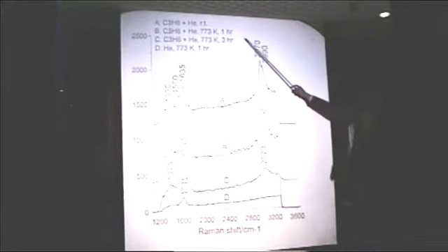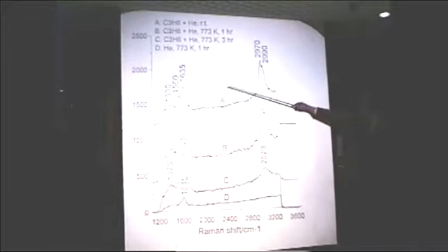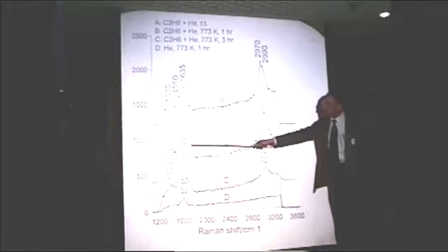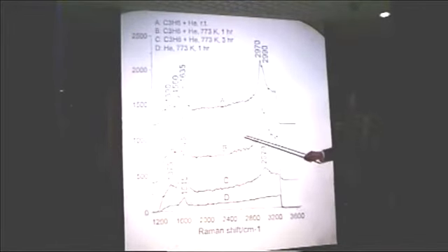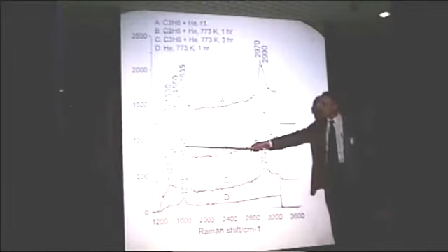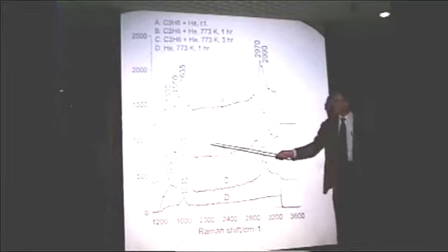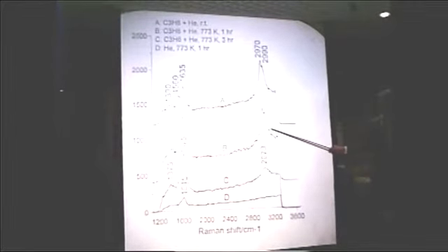All right, so now what we do is we take the material and we heat it at 500 degrees C for an hour in propylene and helium. So we're really trying to coke it up. And basically what you see is that there's some change in the carbon to hydrogen ratio, based on the fact that the CC stretch region bands have grown and the CH stretch region bands are about the same intensity as they were before. But basically not too much has happened after an hour at 500 C.